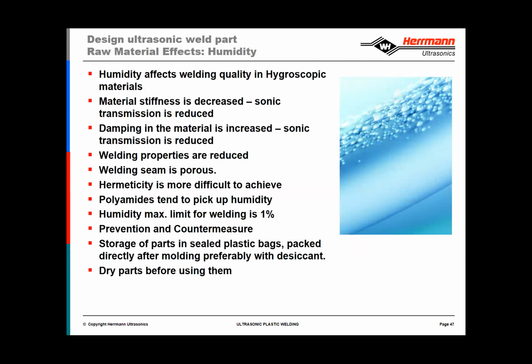Another consideration for your plastic parts is environmental conditions such as humidity. Some materials are what is known as hygroscopic, meaning that they can absorb moisture, especially nylon. So if a material is not dried properly before molding, or the molded plastic part is not stored properly after molding, then the ultrasonic welding process can be inhibited. Water or moisture within the parts requires that the moisture be sort of boiled away, if you will, before the welding happens. So for that reason, if there are parts that you're welding that are hygroscopic, please pay particular attention to handling them properly, sealing them in a plastic bag, or maybe even packing them with a desiccant inside so that any moisture is inhibited from getting into the plastic parts.